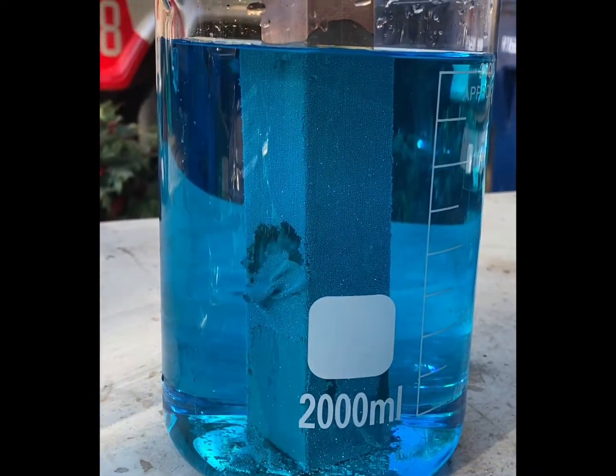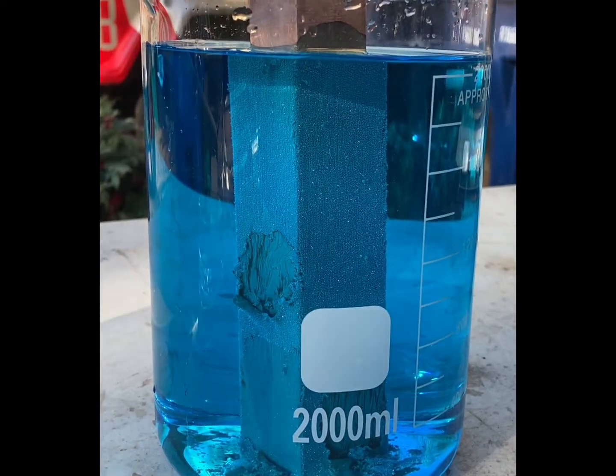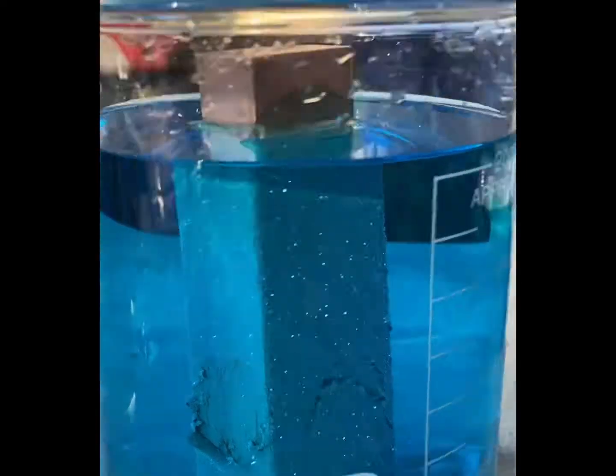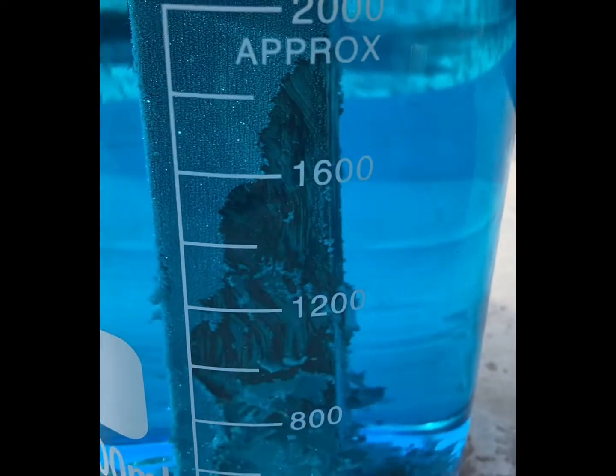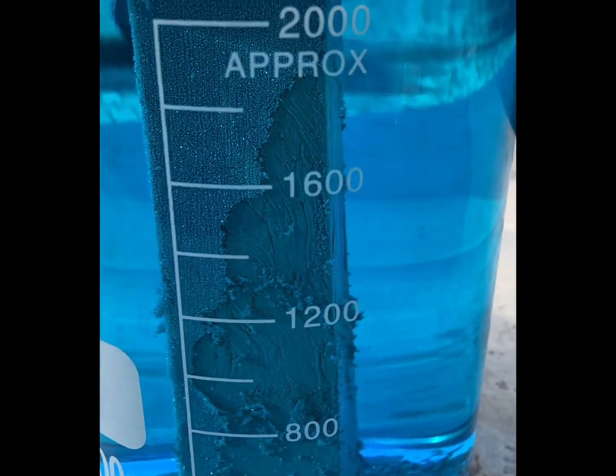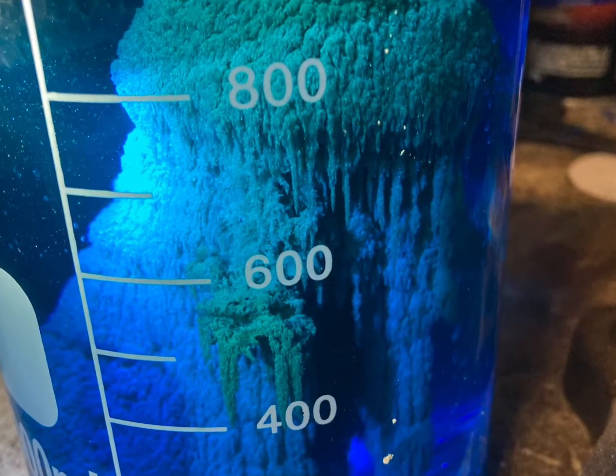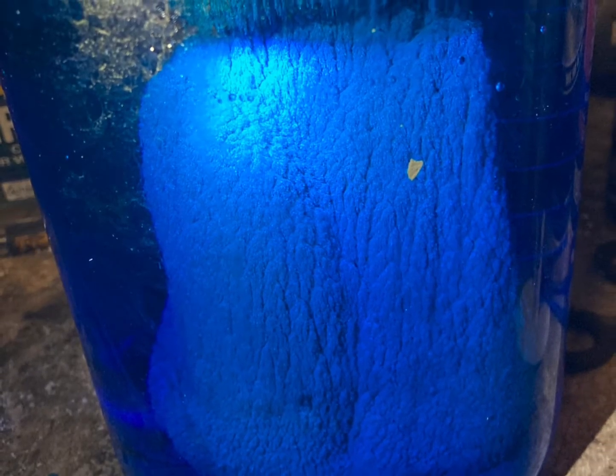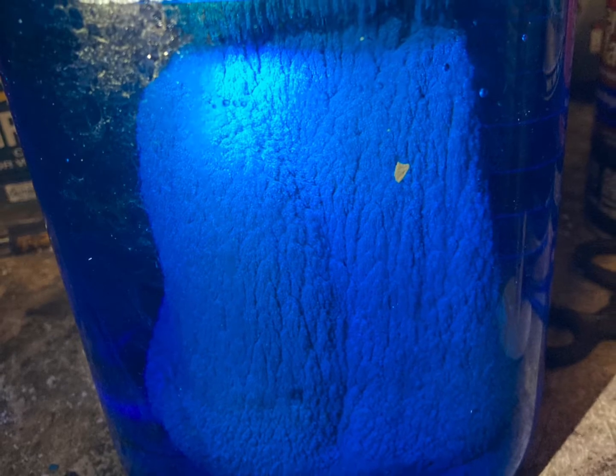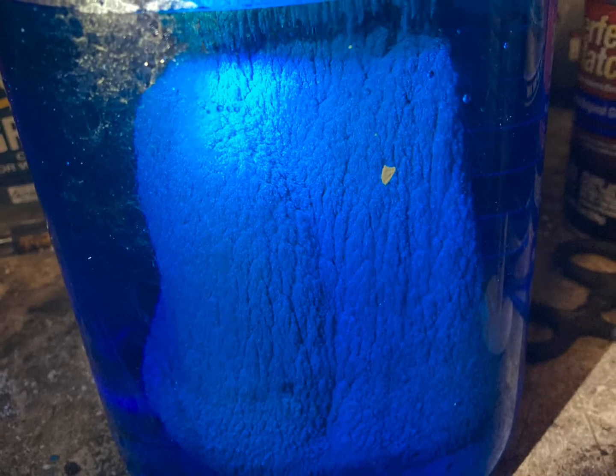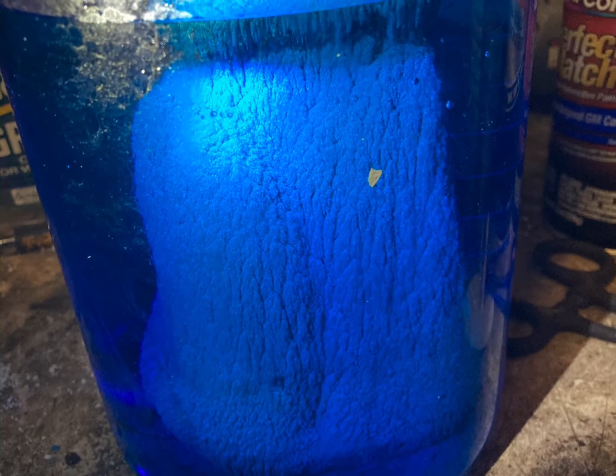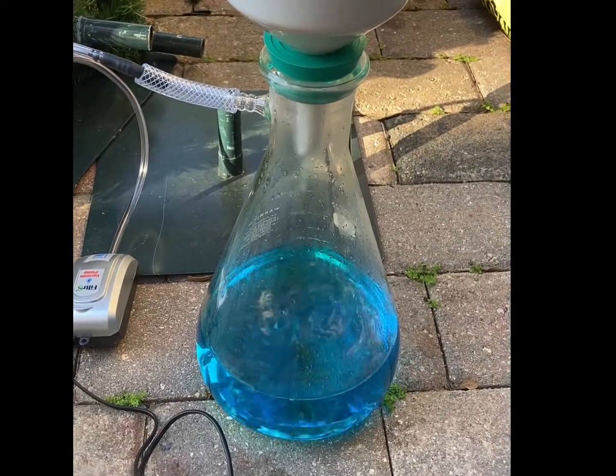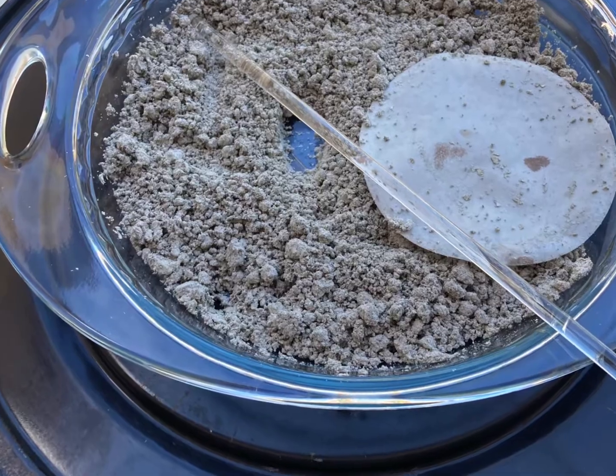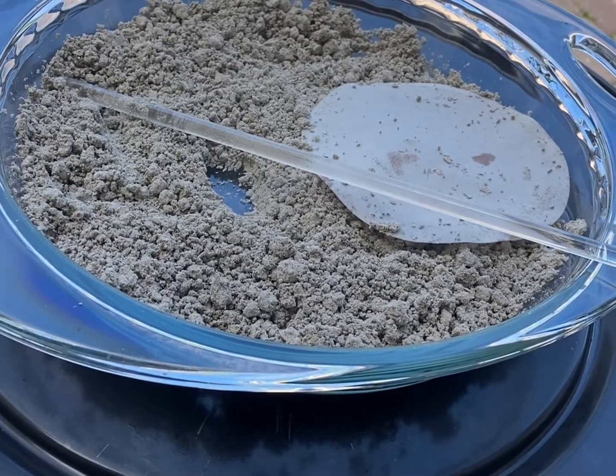It'll take a few hours for most of it to precipitate out, and then you usually leave them overnight. They'll form these big pillows while it's getting all the silver out of solution. Once all the silver is precipitated out, you're going to filter it again through the Buchner funnel with a glass paper until you have all the silver cement really clean. You're going to do that a bunch of times, and then you're going to start to dry it. You want to make sure it's really dry. If there's any moisture in that cement, you've got a pretty good chance of it exploding in your furnace.